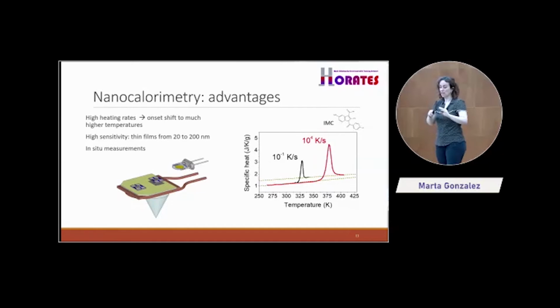I just finished here with the calorimetry, but these high heating rates have something else. Do you remember when I said everything I said, I'm going to use it, the enthalpy curve, that one that was passing the metastable line, and then we had this peak with the enthalpy, and then afterwards we were going back to the equilibrium. I told you that if we go very fast, you pass that equilibrium line. Now we are going at 3 times 10 to the 4 Kelvin per second. We're going extremely fast. So that's what happens.